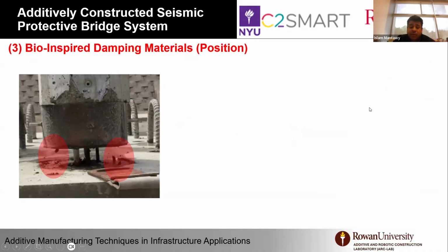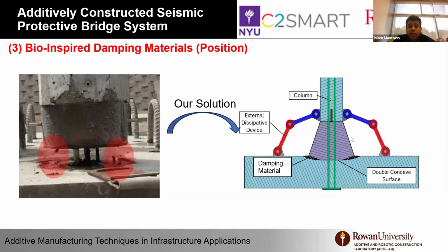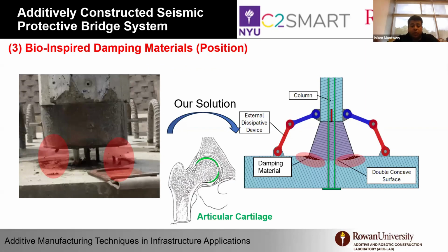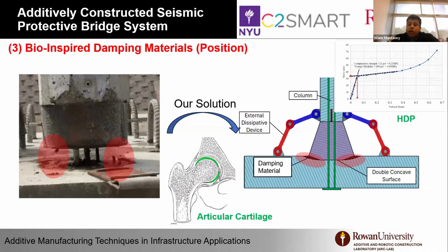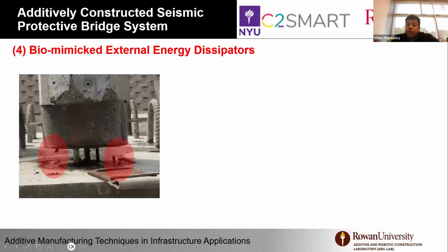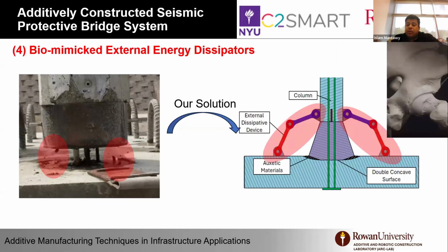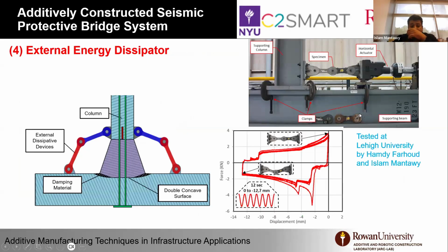We supplemented the energy dissipation using either external elements with rotational capability or packing the gap between the curvatures here with damping materials like polyurethane or other engineered foam. So that is actually similar to what we have for our articular cartilage in our joints. And as I mentioned early on, I was ahead of myself, using external elements that use friction instead of yielding that enable us to activate rocking early on. So we did testing on those elements to verify the energy dissipated as the rocking happened.